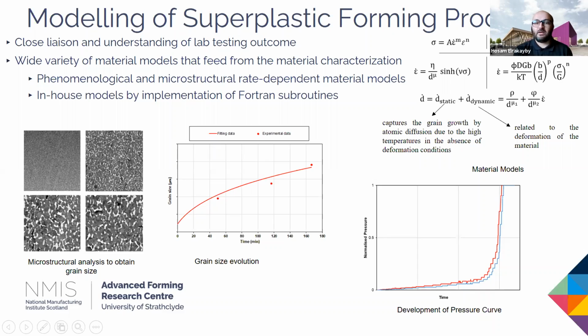Then two steps are usually carried out to calibrate the material model and to model the material response during SPF. Firstly, the microstructural evolution is numerically analyzed by calculating the parameters of the last equation, for example, rho, phi, mu1, mu2. The fitting of the experimental data for the grain size is based on an in-house developed MATLAB script. Secondly, the flow curves are fitted by using the grain size evolution data as an input to the constitutive equation in the top. Once the model is calibrated, it is then implemented into the FE package through subroutines.